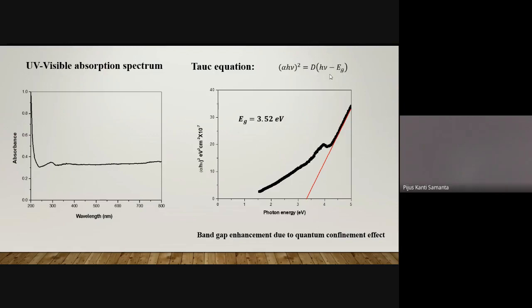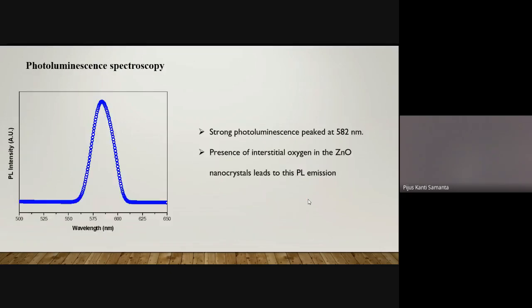And for direct band gap, this exponent is 2, and for indirect band gap it is half. As you know, zinc oxide is a direct band gap semiconductor. We have used this equation, and getting the slope from the high absorption range, we can calculate the band gap to be around 3.52 electron volt.